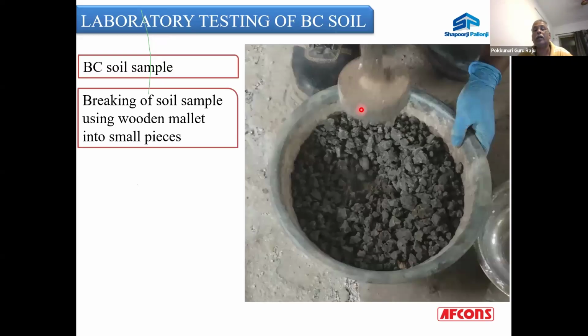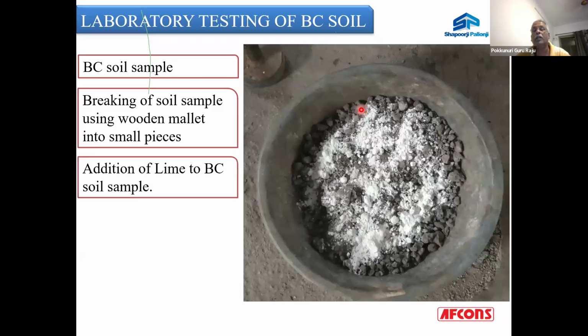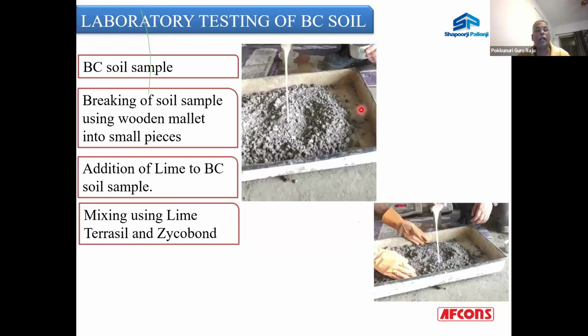Now, the idea is we are working on soil particles with a size limited to 10 millimeters max, not more than 10 millimeters. Now, that ensures that if 10 millimeter particles are being coated, anything within that 10 millimeters is not getting coated, and when it goes as a lump of particles collected together and laid on the surface, your particle to particle contact is not getting crushed much, and even if it is getting crushed, your surface is not exposed to any sort of leakages. Now, once you crush it, you need to add the lime on top of it, depending upon the design calculations, and then you need to add Terrasil and Zycobond one by one.